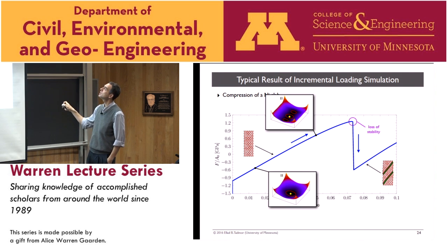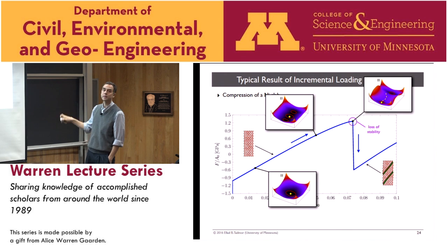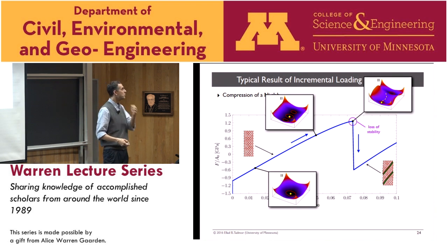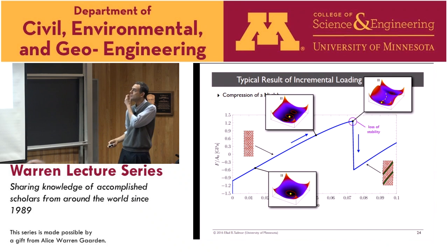But eventually, you get to this point. This is now completely flipped over. It doesn't exist anymore as a stable state. And then you just roll down the hill to a new location, and that's the nucleation that's occurring. It's the same kind of thing that happens with buckling. It's the same idea. All right.